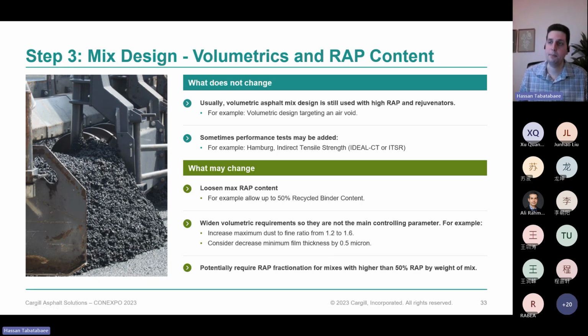Sometimes for higher RAP content, maybe above 50% RAP, you will require a fractionation of the RAP into coarse and fine RAP to be able to control your gradation. Often at less than 40% RAP, fractionation is not commonly done.